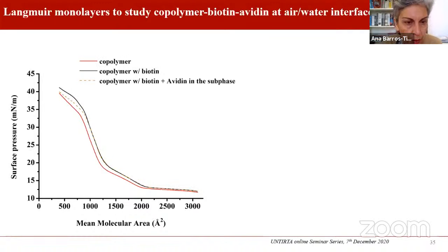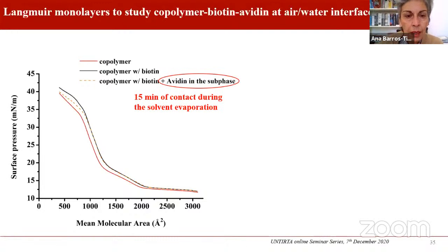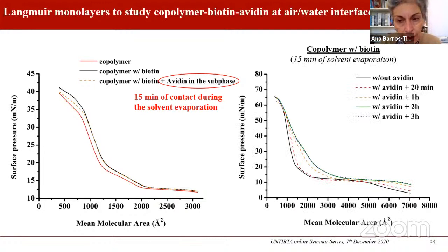So we moved on to testing the copolymer at the air-water interface, the copolymer with biotin at the air-water interface, and finally the copolymer with biotin and after injecting avidin in the subphase. Well, it seems that there is nothing happening. However, this time was very short. The time of contact was very short.